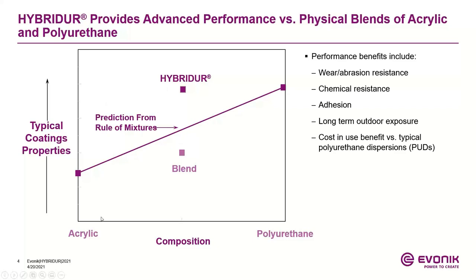Here on the x-axis is a composition of a one-to-one blend of the acrylic and polyurethane, the blends, and the typical coating properties such as the wear, abrasion resistance, chemical resistance, adhesion were measured, and they're compared to that predicted by a linear rule of mixture. These blends and the hybrids, which are Hybridurs, contain equal amounts of the same urethane and acrylic polymers. The phase morphology of the Hybridur polymers is responsible for providing a superior performance when compared to the blend, and that performance is almost similar to the polyurethane dispersions.